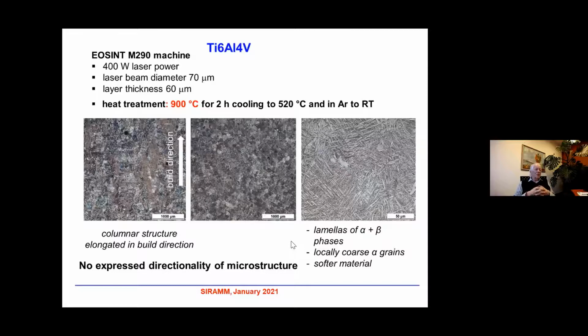So let me show you results on the same material produced on another machine, namely the EOS M290, with 400 watt laser power. Laser beam diameter was 70 microns. Layer thickness was 60 microns. The material after production was heat treated at 900 centigrade for 2 hours, then cooled to 520 in Ar, and then to room temperature. Again, the microstructure, excuse me.